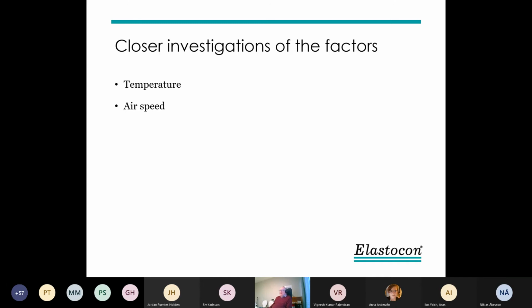Two factors we investigated closely, and that was the temperature and air speed. The air exchange rate had already been investigated in an ISO project where we ran interlaboratory tests, where we had air exchange of 0, 3 times, and 10 times per hour. The standard has specified 3 to 10. We found that there was very little difference between 3 and 10 times air exchange, but if we had no air exchange, we got dramatically different results, or much better results, because the oxygen concentration went down and the aging went slower. So it's always important to have air and the same concentration of oxygen, but also to ventilate away degradation products.